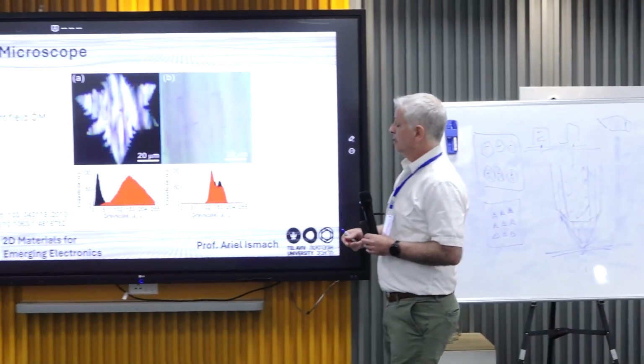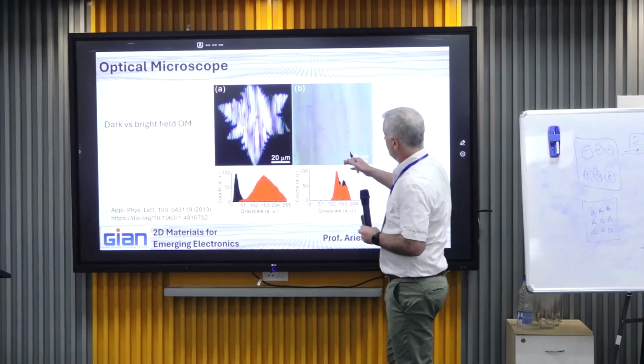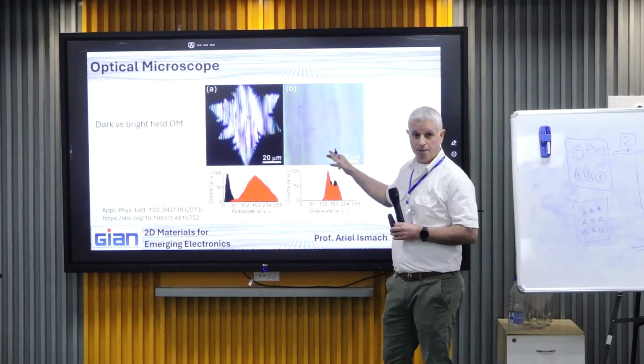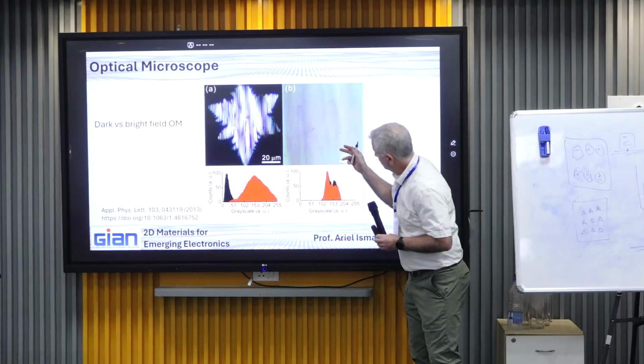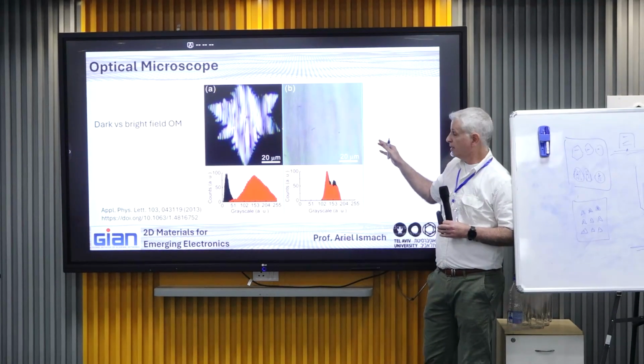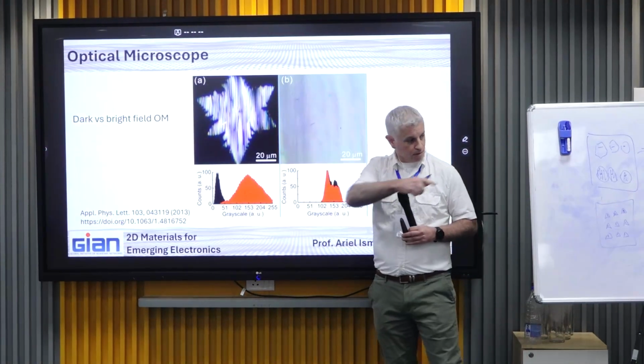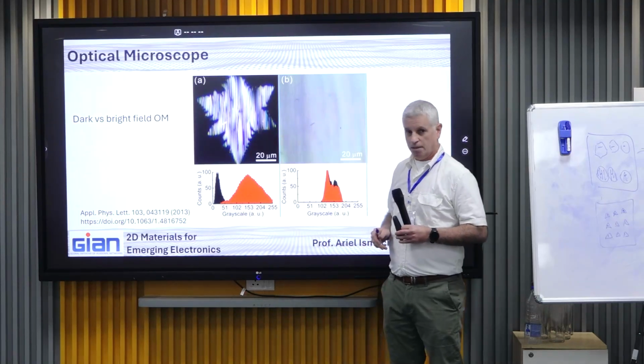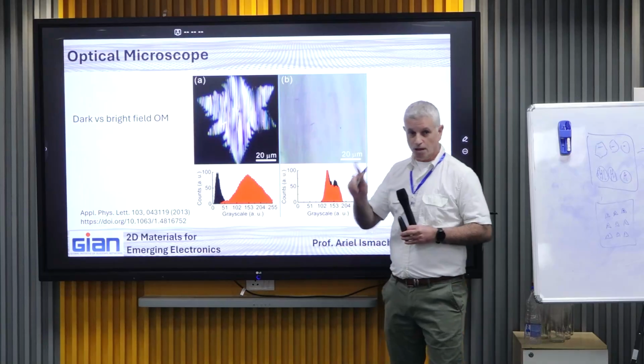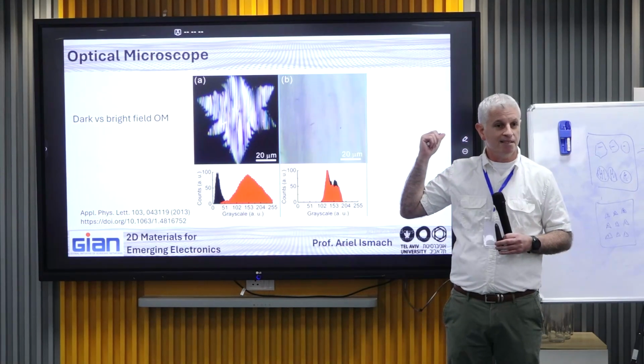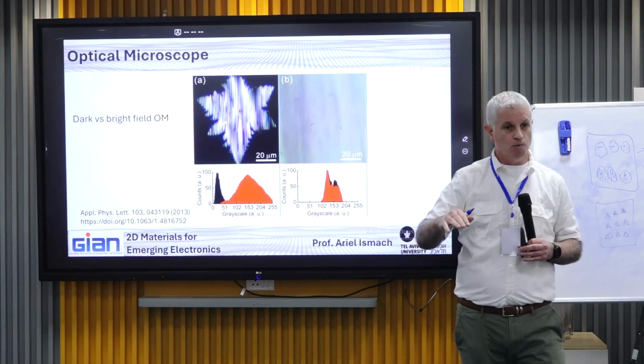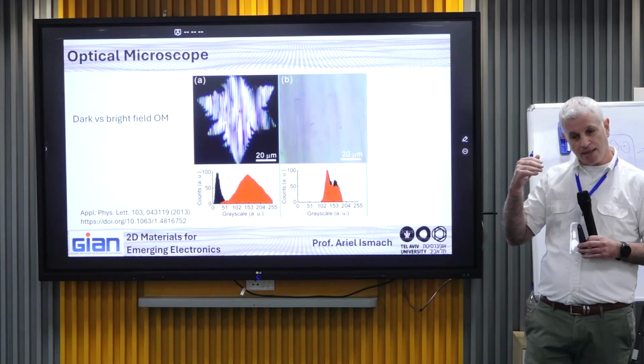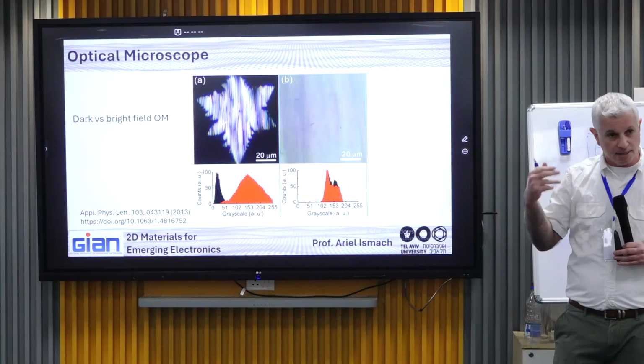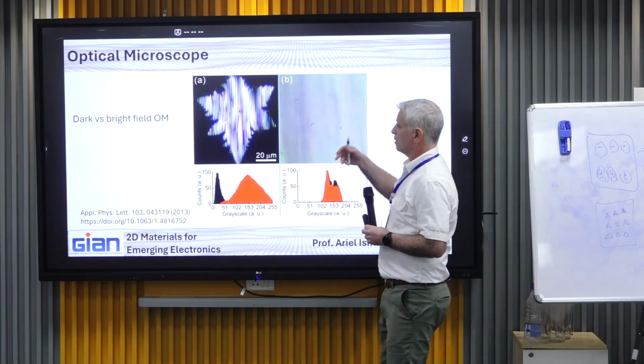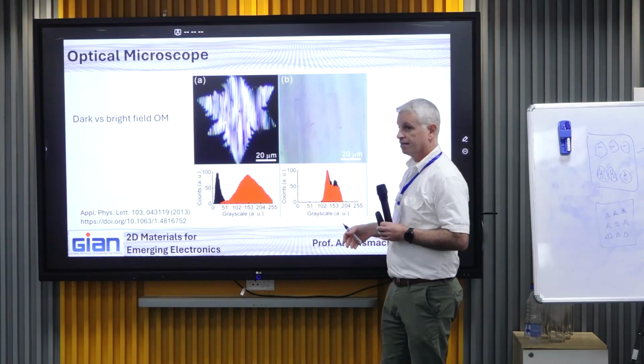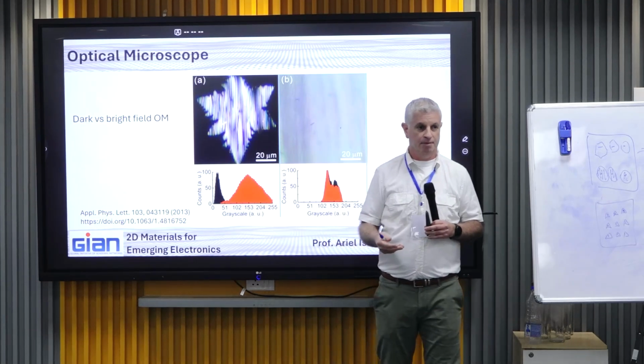So what happens here is, again, what you have is a single layer domain on top of copper. This is bright field. You can see almost nothing, very hard to see anything. But if you do the dark field, this is what you will probably see. What are you seeing here? You are not seeing the graphene. Again, also before we didn't see the graphene. We saw where the graphene is, where the copper is not oxidized. So it's an indirect way to characterize the material, to see that the material is there. In this case, the same. It's not that we are seeing the graphene because of the dark field, but we are seeing what is underneath the graphene.